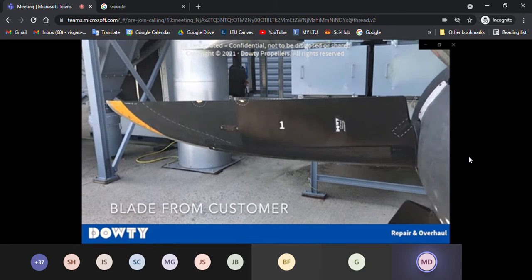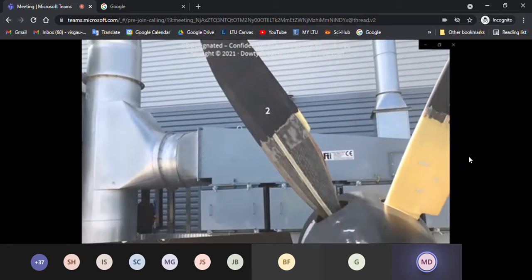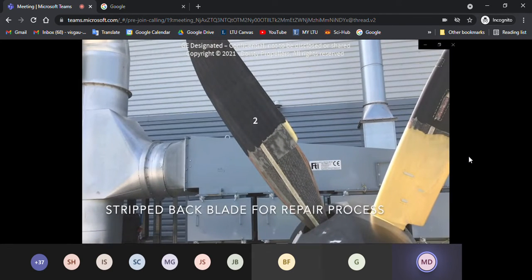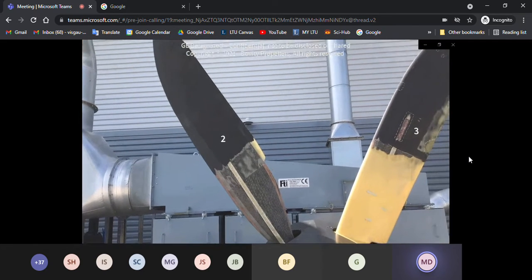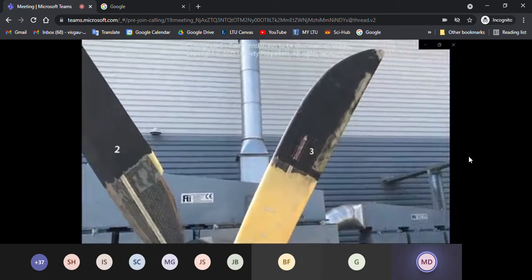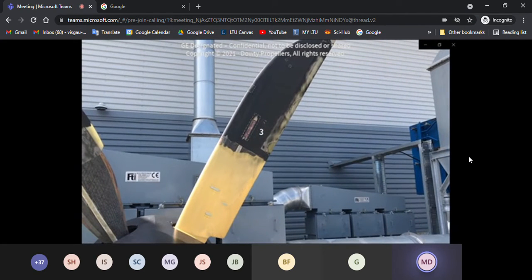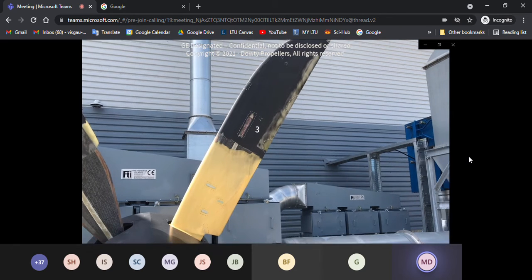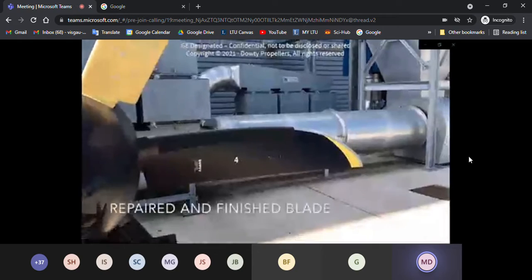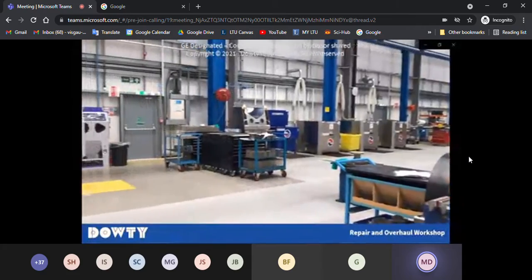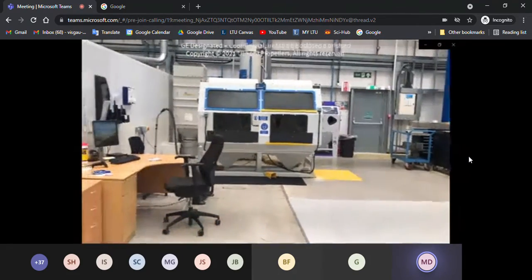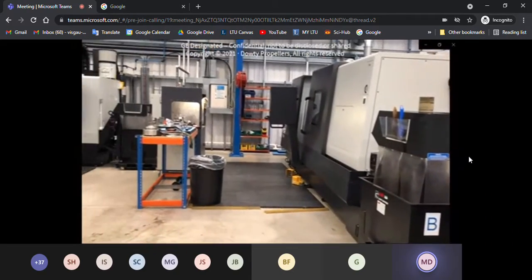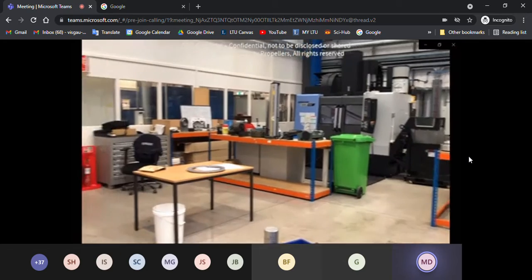So what does that look like in practice? Well, you can see here a blade that's come back from the customer with some minor damage identified. Now you can see the blade when it's been stripped back, ready for inspection and NDT. And a blade that's been repaired, so some minor composite repairs and the cuff replacement. And then a fully repaired and finished blade back to its original condition, ready to go back to the customer. All of this work happens in our repair and overhaul workshop, which is co-located with our OE facility. And we have capabilities for remachining of hubs to tidy up any areas of metallic wear.